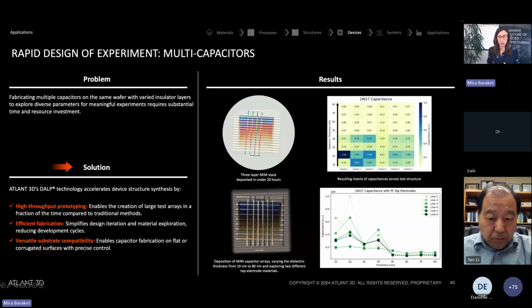So here is an example of a device. In this case, we have created multiple capacitors. This is a metal insulator metal, and what we are trying to do is have a rapid design of experiment. So we are scanning between different deposition processes to be able to find the optimum conditions, or the optimum capacitor in our case. So on the top here, what you can see is a heat map of capacitance versus dielectric thickness. After the depositions that are done with DALP, you are able to characterize the surface, and you can quickly select your optimum processing conditions. The same on the bottom.